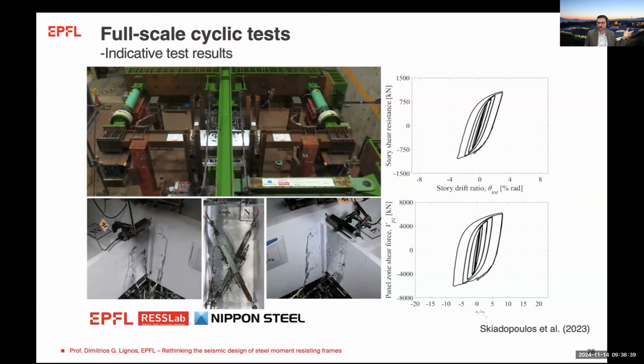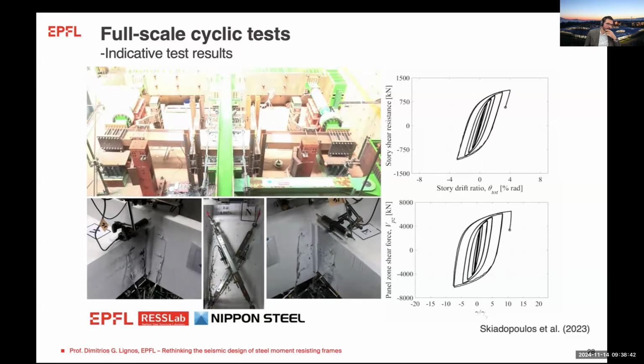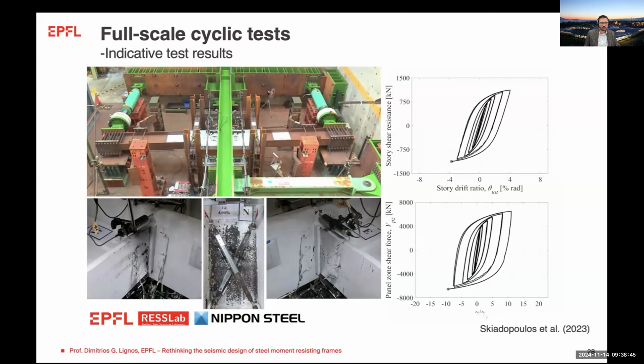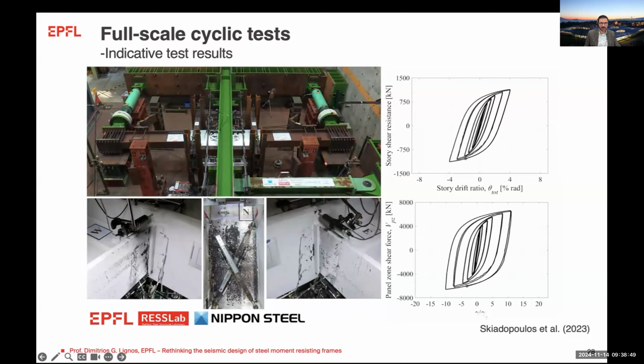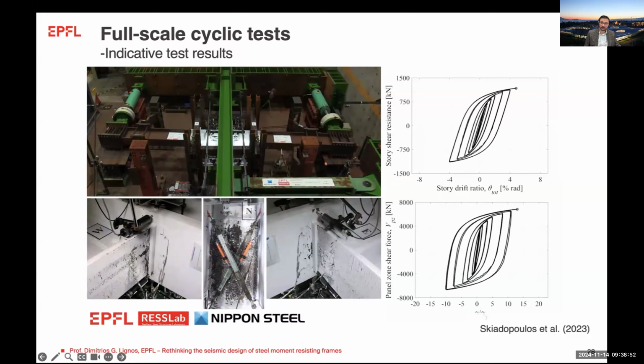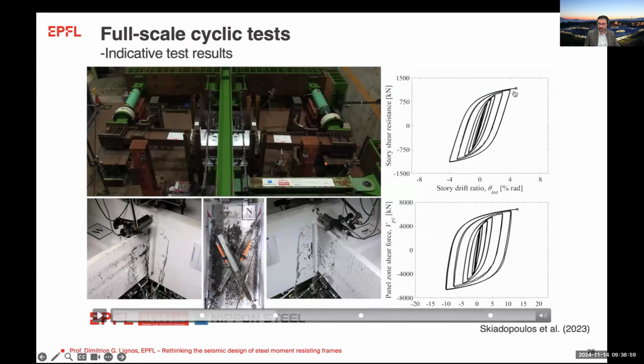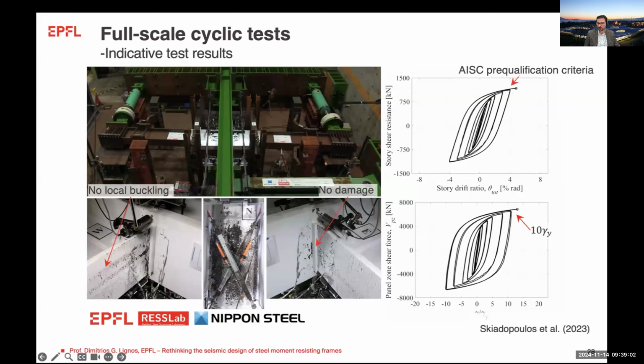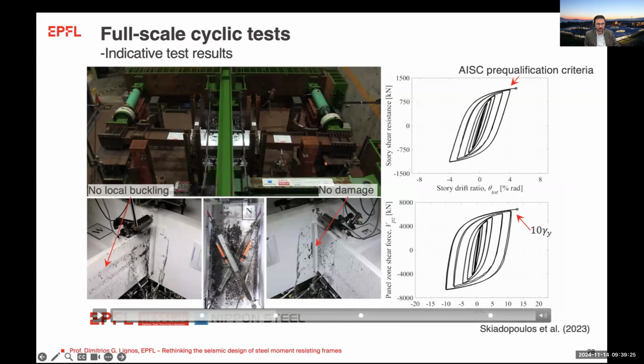Now, if we keep pushing this to pretty much larger inelastic cycles according to the AISC protocol, what happens is that you see obviously that now you get a substantial yielding in the panel zone. The beams start to exhibit again flexural yielding, but again, notice that for a 4% drift that meets the AISC pre-qualification criteria, you get no degradation in the joints, and the panel zone is at 10 gamma Y, and notice that we get no fracture, although we have left the backing bars in place. And in addition, if I inspect the region near the beam flanges, you see that I don't get any buckling, so that would mean that repairs would be pretty much only associated with flexural yielding.